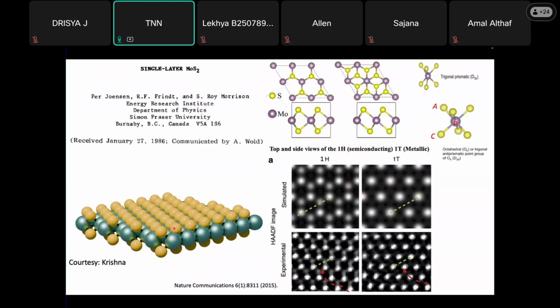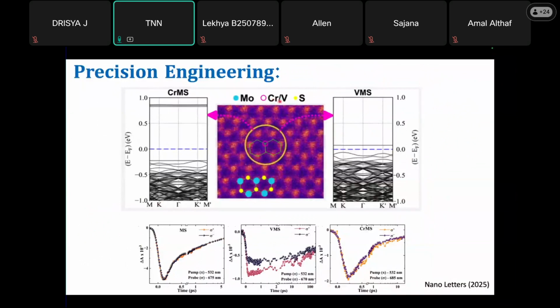Now what I'm trying to say is that I can even replace molybdenum with another element. It can be chromium or vanadium, and we can see whether it is getting replaced or not. There are various ways to see it. The advantage here is that with chromium and vanadium, you can engineer the band structure very nicely. So not only as a semiconductor for electronics, by doing such precision engineering of elemental replacement, you can make them useful for valleytronics too. Valleytronics is another emerging field in data storage, where you can control the band valleys. Band valleys means the higher energies of the valence band or lower energies of the conduction band. Can you control these valleys very nicely?